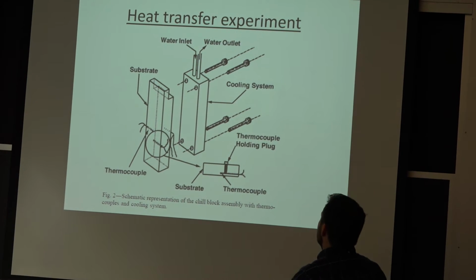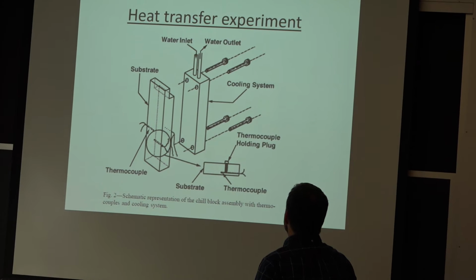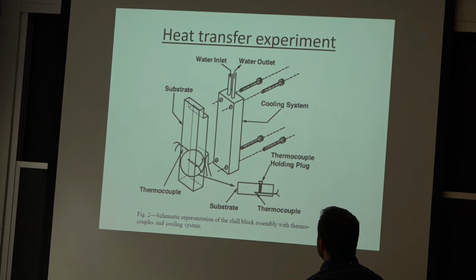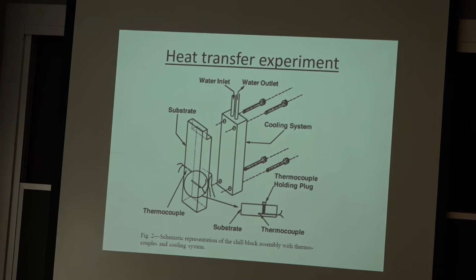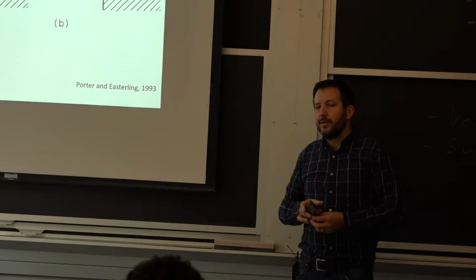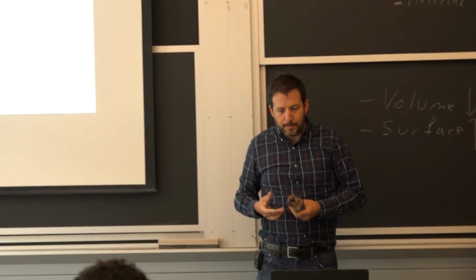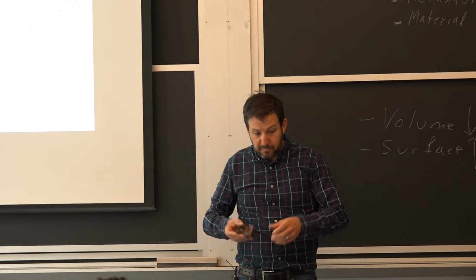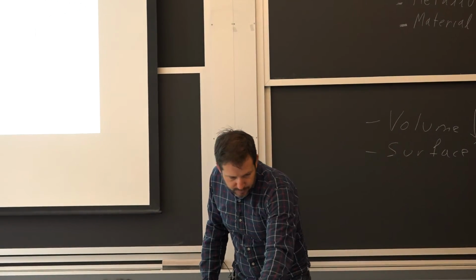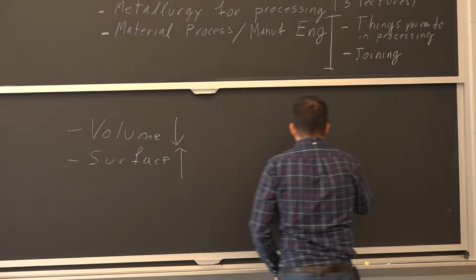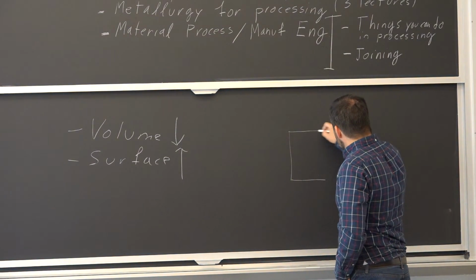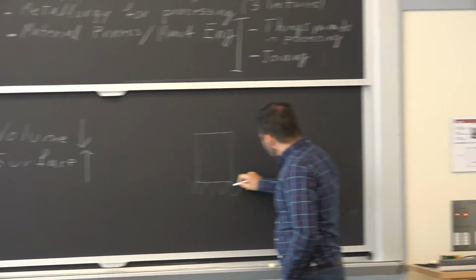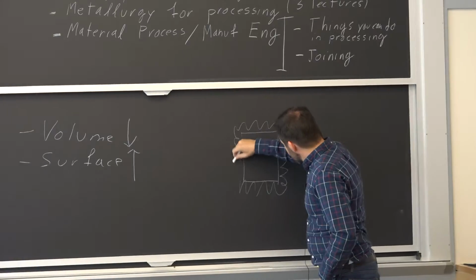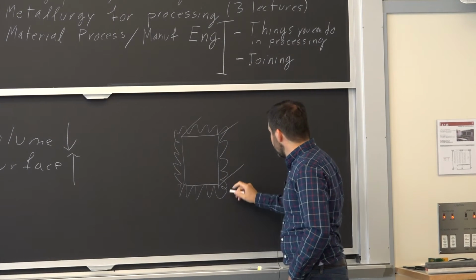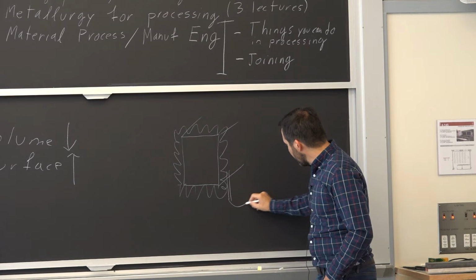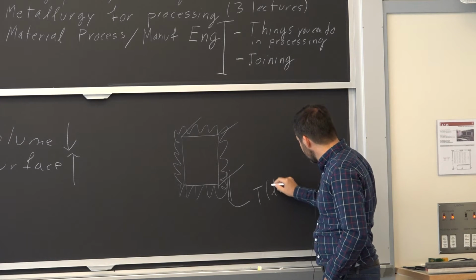Okay. Yeah, this is all closed. There's more complexity here than you probably want to see. But the basic idea is to study solidification and the effect of the mold characteristics. I had to build this fixture where essentially you expose the surface of the metal with the mold. So the mold just looked like this on one side with protection on the edges. And that was just a big box. And behind it, you have these spots where you keep track of temperature. So you get the temperature over time to know what happens.